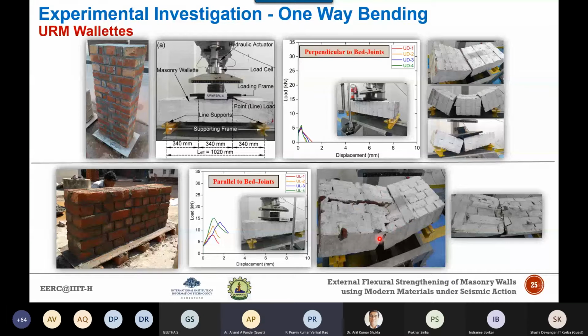The strength degradation in the masonry wallets tested with bending tension parallel to bed joint was a little slower, and therefore the load carrying capacity has increased. Here you can see that the average strength comes out to be 5 kilonewtons, near to 5. If you see the average of these four curves, the average comes out to be in a range of about 12.5 kilonewtons. And therefore, the load carrying capacity parallel to bed joint is increased to about 2 to 2.3 times that in case of bending tension perpendicular to the bed joint.